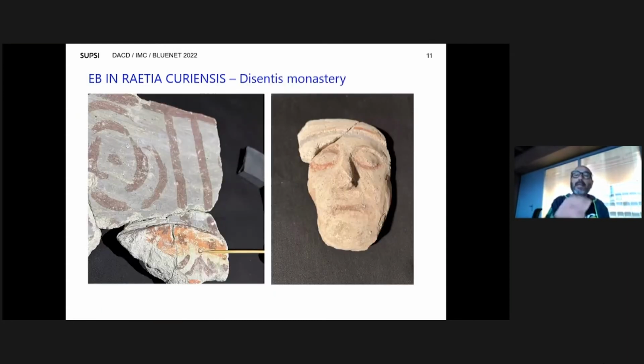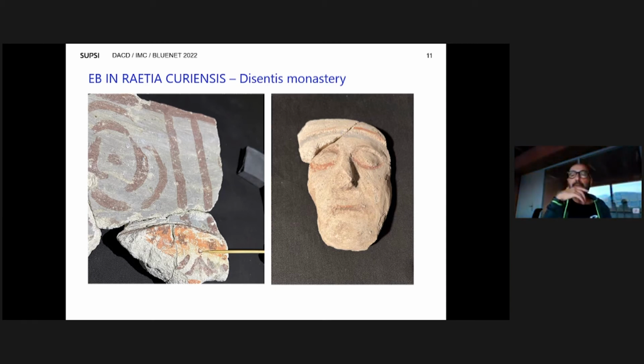So in this monastery, where only painted fragments are available, there is not any evidence of blue pigment, and so there is not any evidence of the presence of Egyptian blue. So most probably here the blue tone of large surfaces was realized using carbon black mixed with lime.